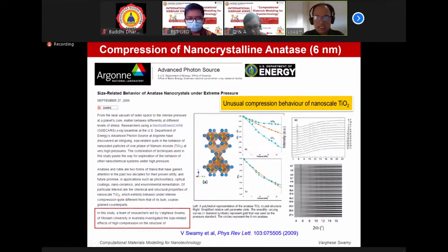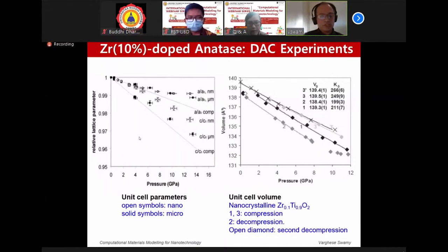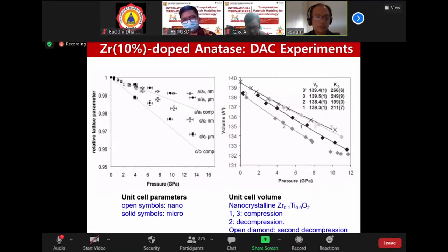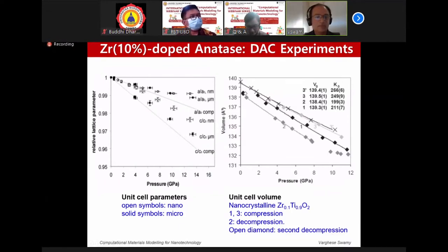Anyway, why am I saying this? It is to show that the behavior of nanoscale material and bulk material are different. And in this diagram, what is shown is similar work, but this time the titanium dioxide anatase is doped with a bit of zirconium, 10% zirconium instead of titanium. You see very similar, very erratic behavior. Normally most materials compress smoothly, but in this case, when you deal with nanomaterial, it compresses smoothly up to a point, and then it flattens, which means it becomes stiffer. So there's a lattice hardening, is the term used, happening at some high pressure.